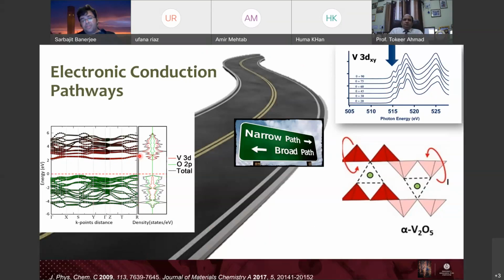But this is a problem because essentially it's a very narrow state. So if you think about this as sort of a highway, if instead of having a highway, you have a very small lane and you have to drive through it, right? It's going to be slow, right? So the electron that localizes in this conduction band has a pretty high mass and has trouble moving through the lattice, right? So this is quite problematic.